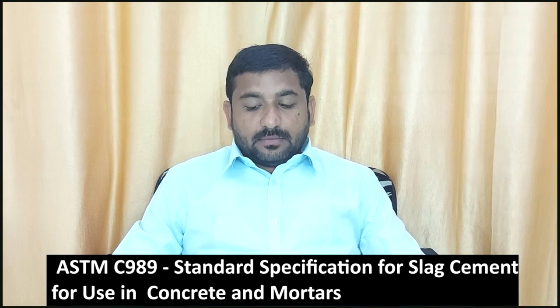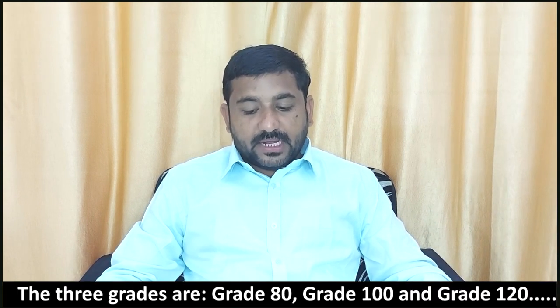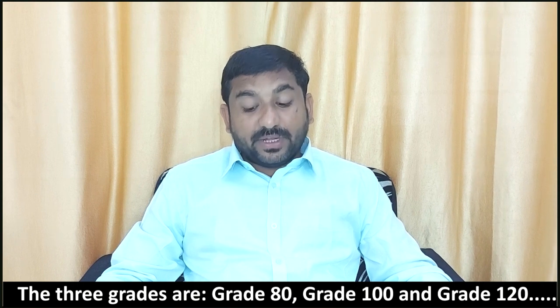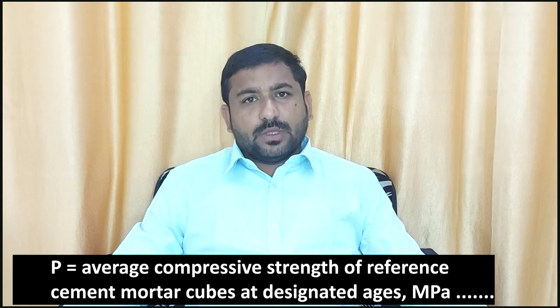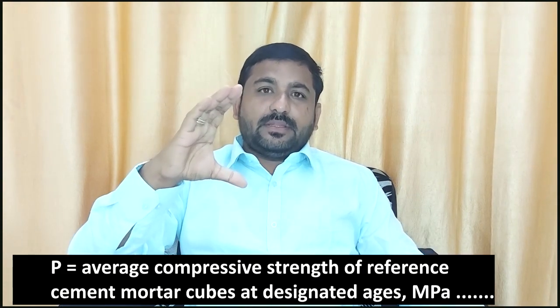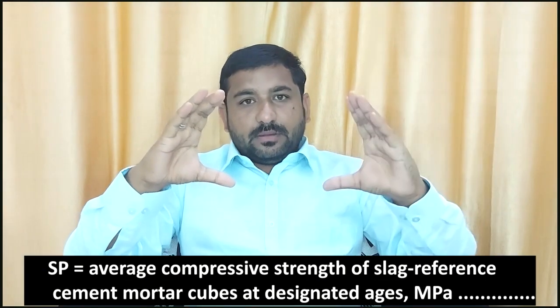Now come to the second point, the activity index, that means the slag activity index. ASTM C989 classifies GGBS into three grades, grade 80, grade 100, grade 120, on the basis of slag activity index. What actually is the slag activity index? It is nothing but one mix with pure hydraulic cement, OPC 53, and another one is the combination, whether you are using 50-50 or 60-40, whatever you are using. So the strength gained by the pure cement concrete is compared by ratio with the blended concrete.